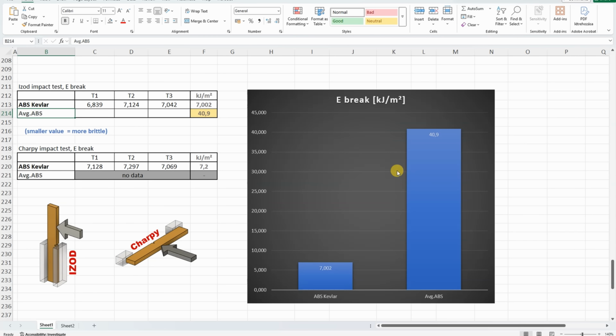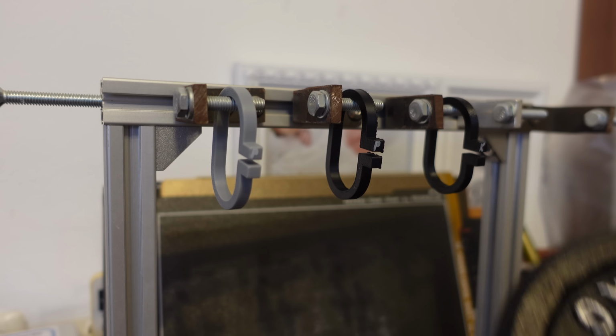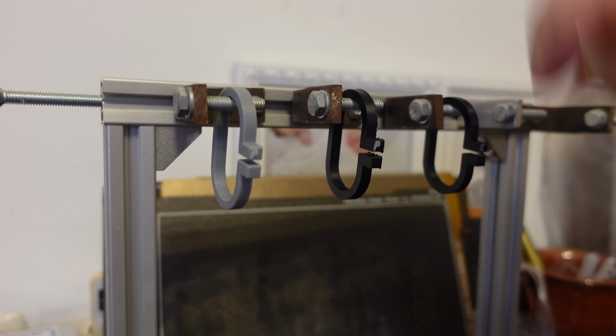But anyway, the toughness is the typical property of no fiber reinforced ABS, and adding fibers will make it more brittle, and unfortunately that's what can be seen here. ABS Kevlar is noticeably more brittle compared to the average ABS, but still tougher compared to the average PETG, for example. Creep test, the deformation on a constant load of 1.25 kilograms.